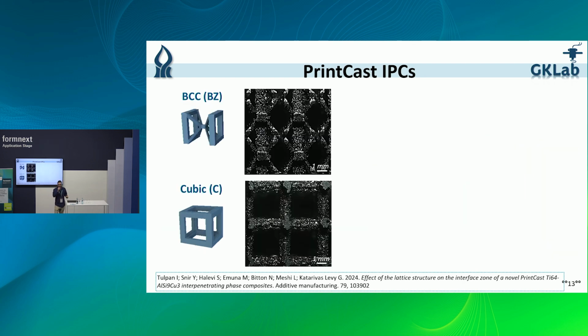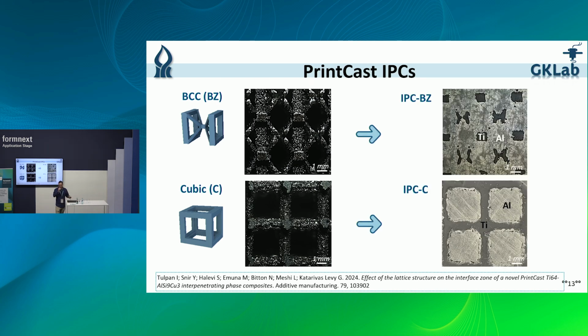Here we can see the actual lattice structures that we printed, and we can see the resulting IPCs after the filling process. In this type of process, there are two main challenges that we overcame. The first challenge is the very act of filling up the pores of the lattice structure, since the aluminum alloy does not flow very well inside the lattice structure. And the second challenge concerns the bond between the aluminum matrix and the titanium lattice structure.